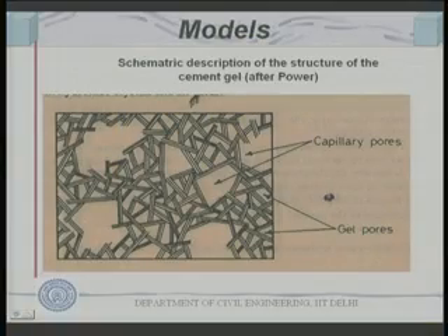If you add more water, then more such space will remain vacant, and this space is called capillary pores, because their sizes are larger and they are between the C-S-H gel structure. So, there is a gel structure, and in between you have capillary pores. Within the gel itself there will be gel pores, which are finer in size. So, that is the model given by Powers.